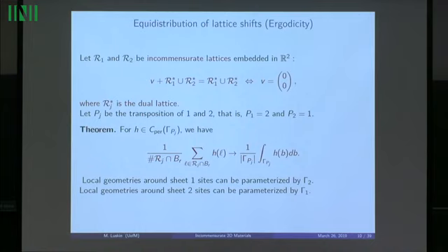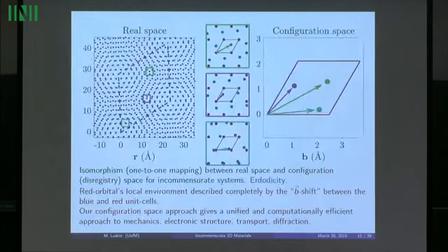That's called a site energy, and the energy of that atom depends on the displacement of all the atoms around it. So H is going to be one of those site energies. This is how we move from our atomistic model to our continuum models.